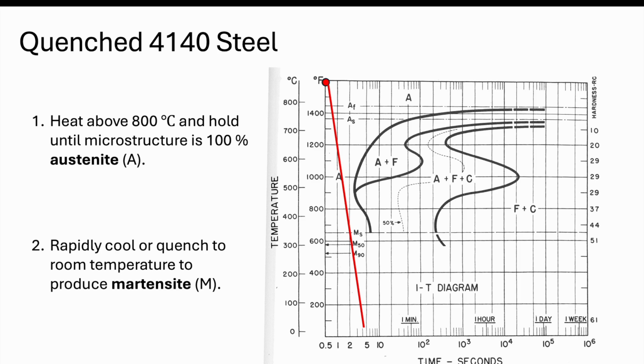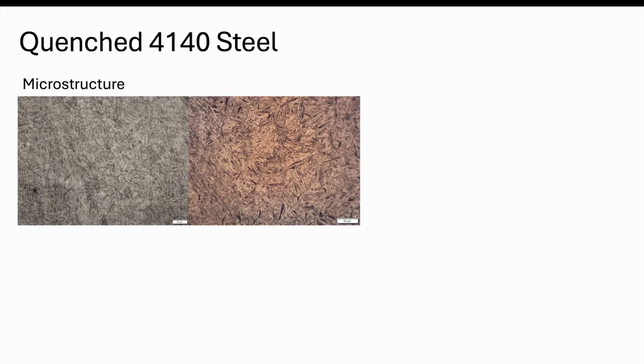So now we want to look at what results from this. And again, this is real results that we have in our lab. I'm going to walk you through what we see. For the quenched 4140 steel samples, we get a microstructure that looks like this. These are two different images taken at different points. But one thing you'll notice is a lot of individual, very small needles or thin lenses almost. This is very characteristic of martensite.